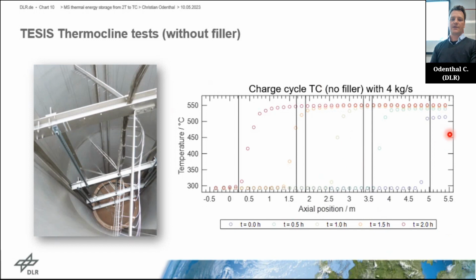In that case, we started off with almost the lowest temperature level, and then added hot molten salt. After about 2 hours, you have a fully charged storage tank, as you can see here from the progression of the temperature profiles.